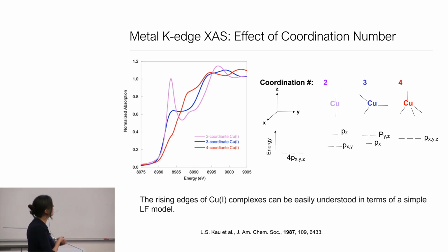And so we can start with copper, just a naked copper 1 ion, where the 4p xyz orbitals would be degenerate. Now imagine that I bring in 2 ligands along the pz axis. Due to antibonding interactions, I'm going to raise the energy of the pz, and it's going to become antibonding, and I'm going to have a low energy xy that's doubly degenerate. And so the intense transition we see here is actually to a doubly degenerate pxy in a simple picture. But actually, nicely, you can also show this these days with ORCA TD-DFT calculations, which nicely reproduce this.